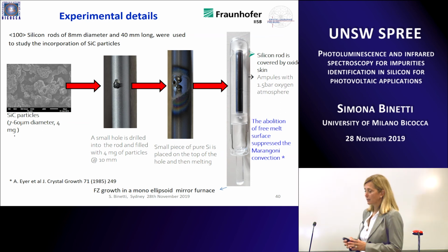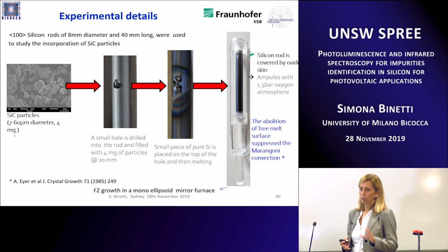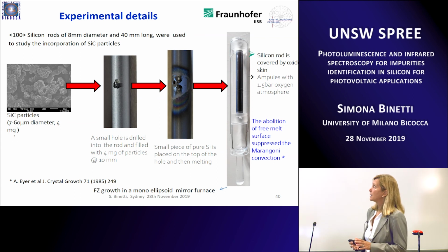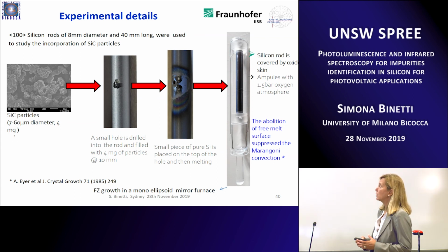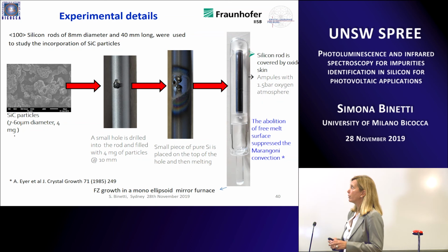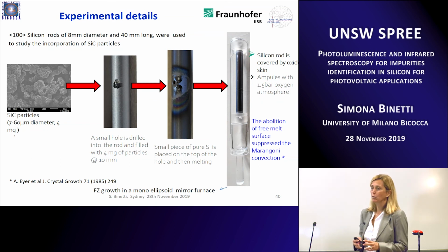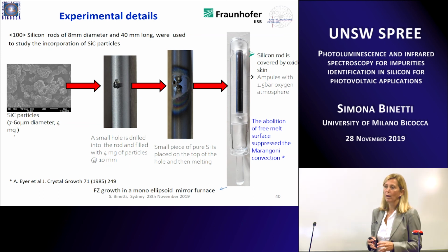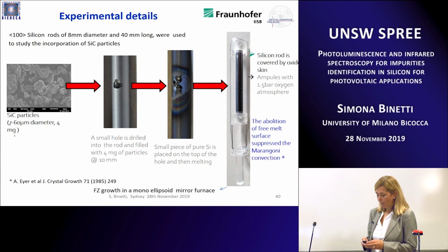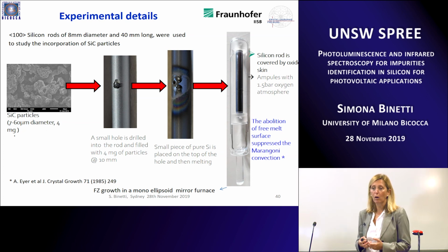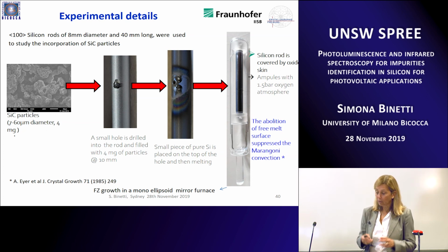covered by an oxide skin. So the skin will be the source of oxygen as well, but it was created in order to have an abolition of the free melt surface, and so in this case you have a suppression of convection, of Marangoni convection motions, and you have a pure diffusive transport mechanism. So it's a sort of ad hoc microgravity condition growth process.